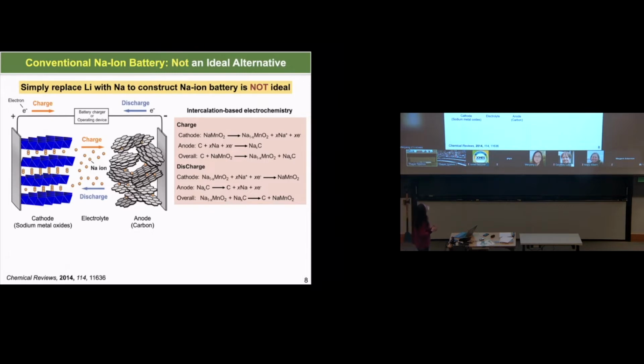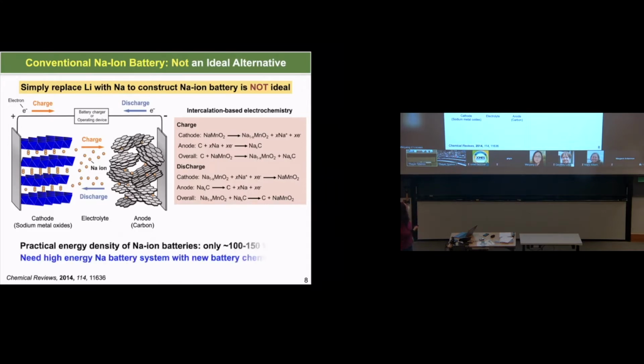So similar to the current lithium-ion system, where you have lithium here, you replace lithium with sodium with a similar mechanism. What you get is a battery we call the conventional sodium battery. However, you do increase the total weight of the battery system because sodium is heavier. The practical energy density we can get from a conventional sodium-ion battery is in the range of 100 to 150 watt-hours per kilogram.